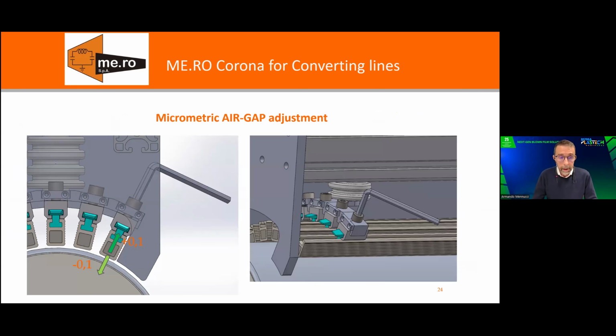Then in this slide we show how we can set the gap. There is a micrometric adjustment that allows a very fine adjustment, more precise than 0.1 millimeter. This is very important because on a ceramic bar system, the uniformity of the gap and the precision of the gap is very, very important. Otherwise, you risk having a non-uniform treatment along the width. This is very, very important.